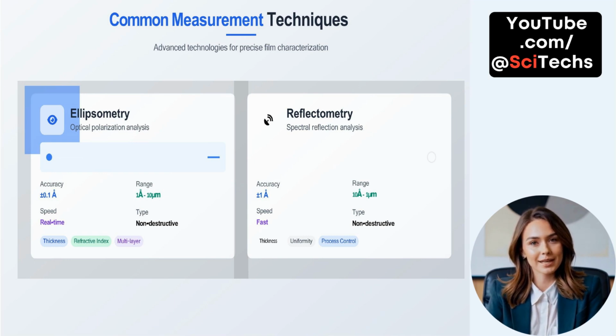Reflectometry, on the other hand, analyzes spectral reflection to assess film properties. Though slightly less accurate, at plus or minus 1 angstrom, it is still highly reliable and fast. Its measurement range typically spans from 10 angstroms to 1 micrometer. Like ellipsometry, it is non-destructive and supports both thickness and uniformity evaluation. Reflectometry is also widely used for process control. Together, these tools help ensure films meet specifications, contributing to high yields and reliable device performance.